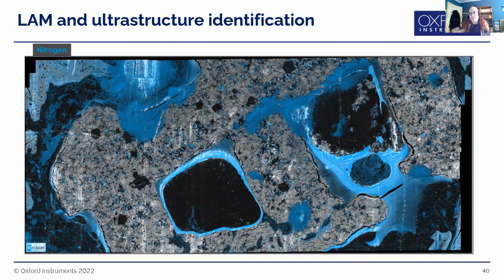Now, this is the nitrogen maps superimposed over the electron data. And immediately you can see where there are clusters of nitrogen within the hydroxyapatite implant. Now, hydroxyapatite does not contain nitrogen. It's calcium and phosphate. So you wouldn't expect to see nitrogen. So everywhere we're seeing nitrogen here is indicative of cellular material. And we can also have a look at the uranium signal. Uranyl acetate targets DNA and various other biomolecules. And you can see that the uranyl acetate signal also overlaps greatly with the nitrogen signal.